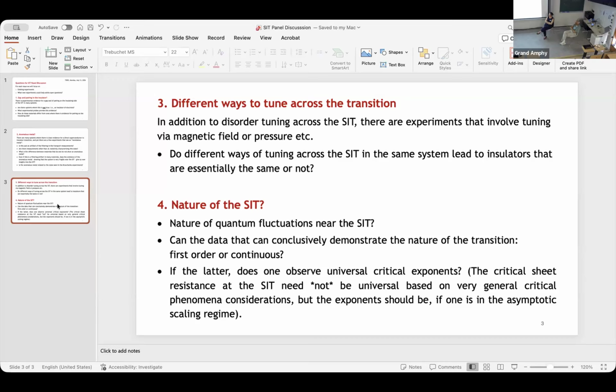For what concerns disordered thin films, yes, it's true, because the filters can be better and better. So one way is just to use better and better filters at ultra low temperatures. The other way is to study the sample with a high temperature anomalous metal state. For example, at 10 Kelvin, 20 Kelvin, you just use normal filters, it's okay. You don't need to worry about noise from outside. But if you study a TC around 1 Kelvin, then you study the anomalous metal state at 0.1 Kelvin, you should consider how to try your best to exclude the noise effects.